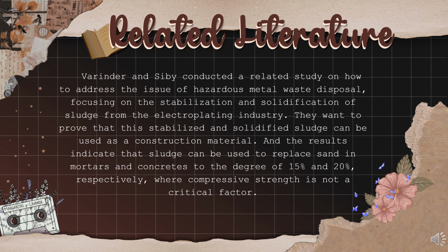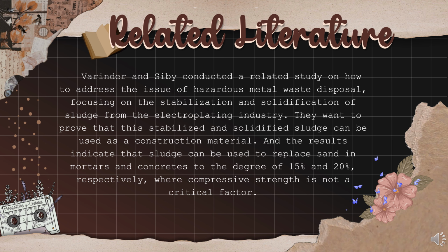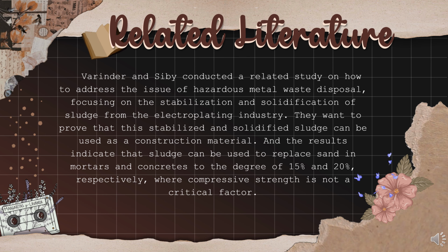Varinder and Siby conducted a related study on how to address the issue of hazardous metal waste disposal, focusing on the stabilization and solidification of sludge from the electroplating industry. They wanted to prove that this stabilized and solidified sludge can be used as a construction material, and the results indicate that sludge can be used to replace sand in mortars and concretes to the degree of 15% and 20% respectively, where compressive strength is not a critical factor.